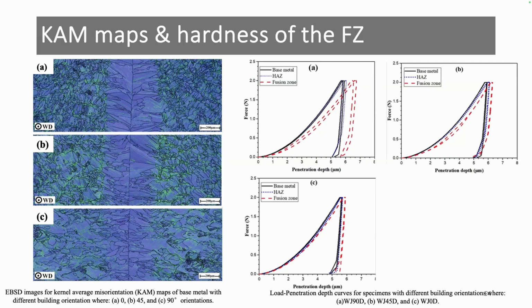Therefore, we can see that the hardness value of the fusion zone of this 90 degree WJ, the weld joint 90 degree, is lower than the base metal. However, here in the WJ0D, the values are very close between the base metal and the fusion zone. And also the main reason here is related to the cooling rate after welding, which makes that grain size to be smaller than grain size in fusion zone of 90 degree.